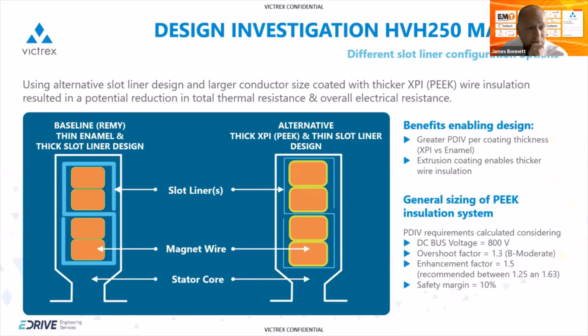The engineers at eDrive also then proposed to use this free space in the slot to increase the copper conductor size. So therefore, by using an alternative slot liner design and a larger conductor size, along with a thicker XPI wire insulation, this resulted in a potential reduction in the total thermal resistance, as well as the overall electrical resistance, which has potential to improve the motor efficiency and the torque density.